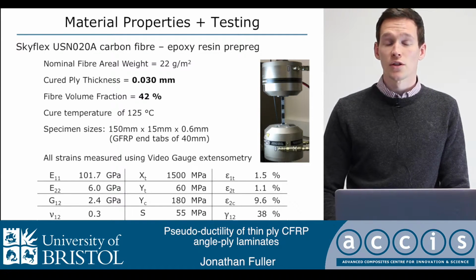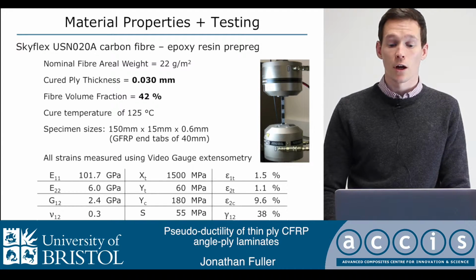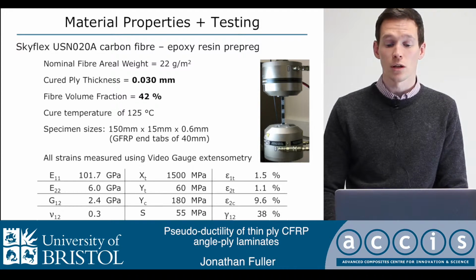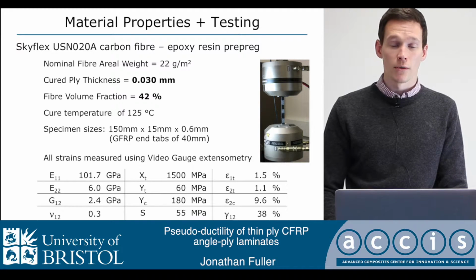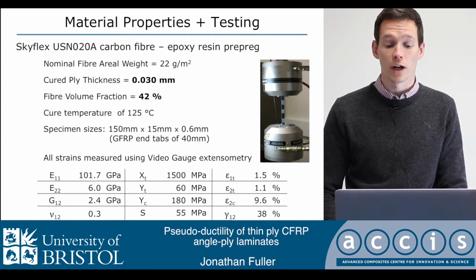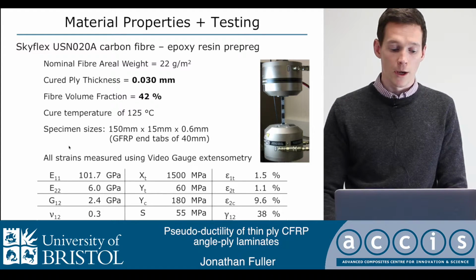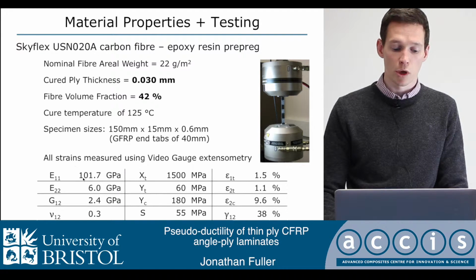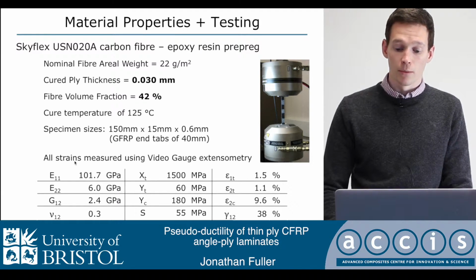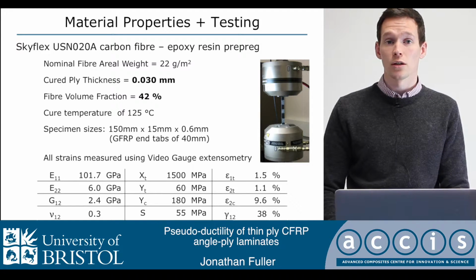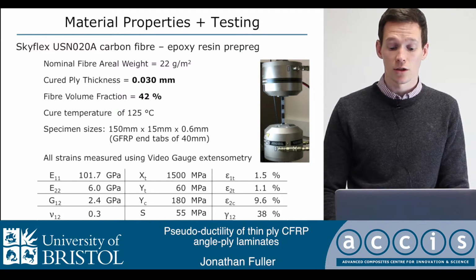So the material I've been using for this work is a carbon fiber epoxy prepreg of 0.03 millimeter ply thickness. The thing to note here is it's a very low fiber volume fraction of 42%, which then leads on to the rather low Young's modulus shown by the more. And the other thing to note is all the strains have been captured using video extensometry.